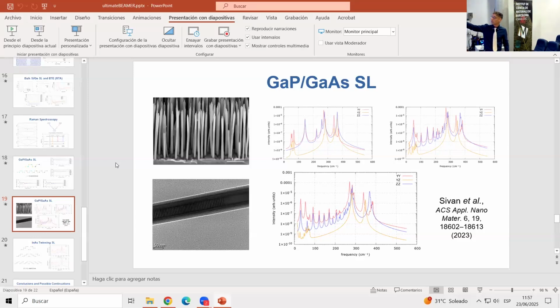And indeed, we compared our simulations with the experiments in the paper I mentioned there. The problem with that is that the longest period that we could simulate was still slightly shorter than the shortest period that they could grow in the experiment. So there is some compatibility, there is some correspondence, we were happy with that, but you cannot just expect the two pictures to overlap and that's it. Okay, I think that's fine for now.